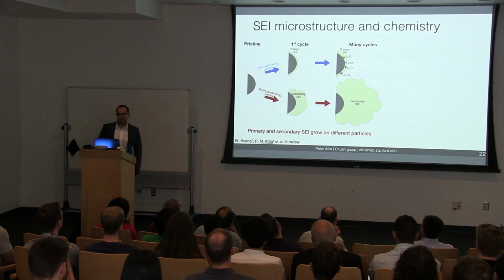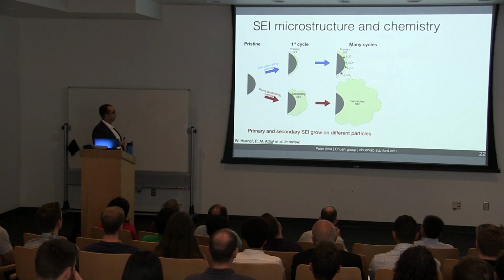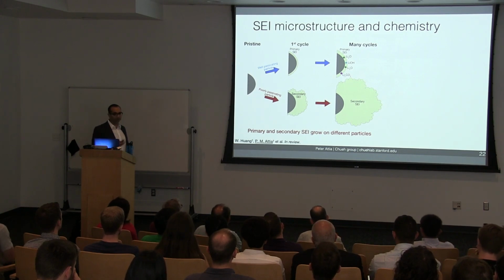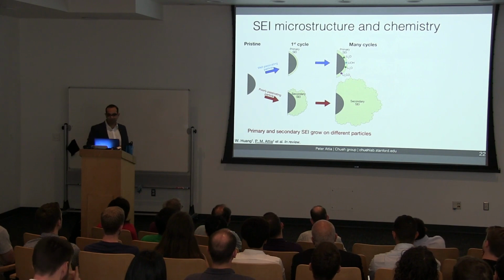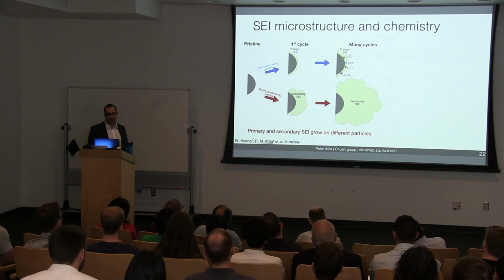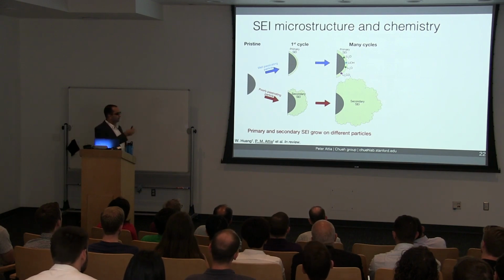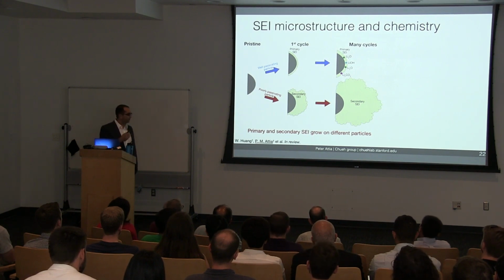So if we summarize our findings of SEI microstructure and chemistry, we see two distinct types of SEI emerge. On some particles, we see this nice, well-defined primary SEI. It's only a few nanometers thick, which is good because it means it didn't consume that much lithium. After many cycles, we see a slightly thicker SEI with crystalline inorganic components embedded inside. And it's possible that these crystalline inorganic components contribute some sort of passivity ability to prevent further SEI growth. In other particles, however, we see this large amorphous secondary SEI that gets bigger and bigger with cycling.